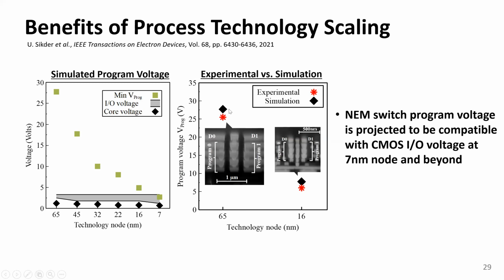But it matches what we predict from experimental simulation. 65 nanometer node, and also later on we used TSMC's standard 16 nanometer node to fabricate even smaller switches. And as the air gap gets smaller, the actuation voltage goes down. So we can project that as we use more advanced technologies with smaller and smaller pitch, in other words, smaller and smaller air gaps, the switching voltage of these NEMS devices can become compatible with CMOS transistors, approaching 1 volt, just to change the state of this reconfigurable interconnect.